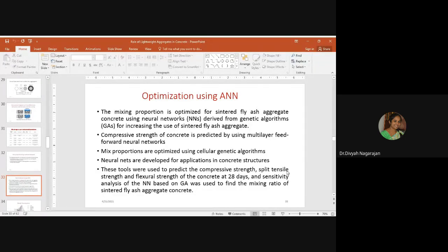The mix proportion, first, genetic algorithms were used for making neural networks. The compressive strength of the concrete is predicted by using multi-layer feed-forward neural networks. Mix proportions were optimized using cellular genetic algorithms. Neural nets were developed for applications in concrete structures. These tools were used to predict the compressive strength, split tensile strength, and flexural strength of concrete at 28 days. And also sensitivity analysis based on genetic algorithm neural network was carried out to find the mixing ratio of the sintered fly ash aggregate concrete. Initially, I performed a lot of trial mixes. Then, from literature reviews, the values were taken down and applied in the optimization technique.